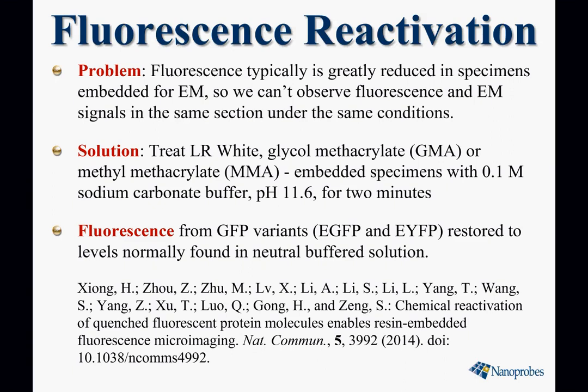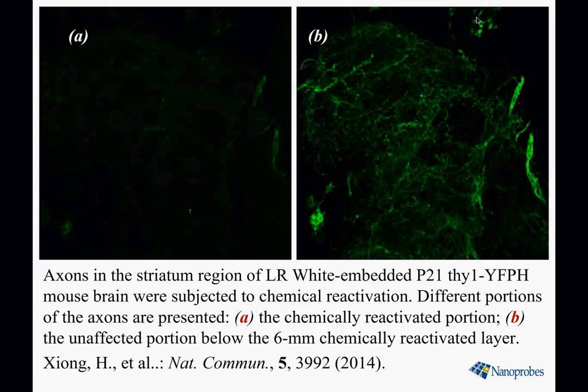Fluorescence can be reactivated by certain chemical conditions. And typically it's reduced in specimens embedded for EM. So it's hard to observe fluorescence in EM under the same conditions. But LR White, glycol methacrylate, or methyl methacrylate embedded specimens that are treated with 0.1 molar sodium carbonate buffer at basic pH, 11.6, for 2 minutes, will restore the fluorescence. And the fluorescence from GFP variants, like EGFP or EYFP, can be restored to levels normally found in neutral buffered solution by this method and this approach. And again, here's the reference for that. And here's an example showing chemical reactivation of fluorescence by this method.